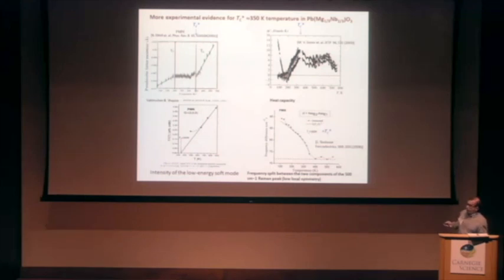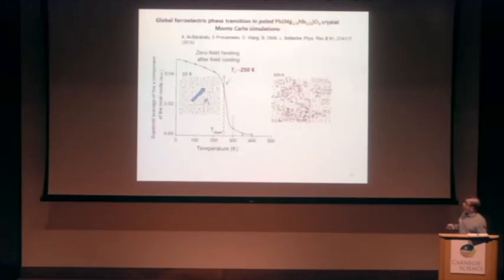And these are some experimental results showing that something happens at this TC star temperature, 350, from different experimental data. These are all experimental data, and everywhere you can see that the anomaly exists at this temperature. But what happens at lower temperature? These are the results of previous Monte Carlo simulations.